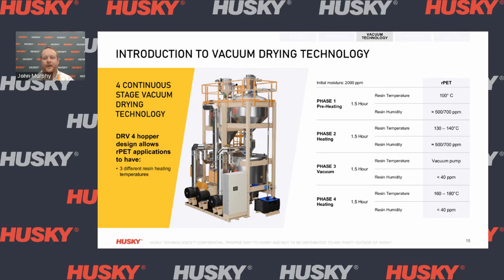In phase 2, we're heating up to 130 to 140 degrees, and we have no change in humidity level. In phase 2, it's a closed loop heating system just designed to increase temperature, not to remove any humidity. In phase 3, there is no change in temperature, but the material is exposed to that vacuum level, which is able to suck out the remaining moisture down to below 40 ppm. And then lastly, in phase 4, we have another closed loop heating system. So there's no change in humidity level, but we're able to increase the resin temperature up to 160 to 180 degrees, depending on what is best for your process.